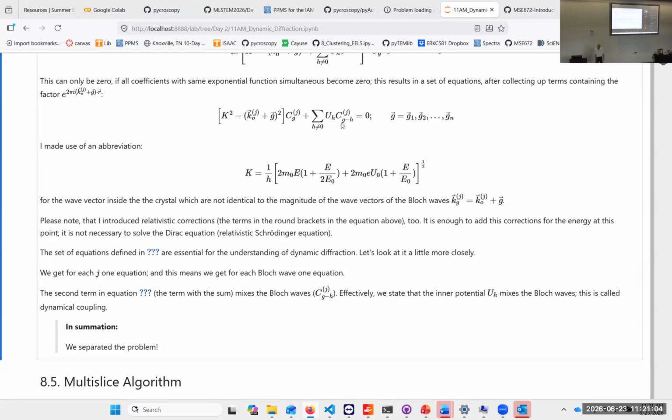So we have the first one going, and in our simple picture this one is connected with a spring. Then at some point the second one starts being activated, so we get diffraction. And funny enough, at some point all the intensity is in the second pendulum, our diffracted beam, and then it gives it back. So with two pendula, I can do that with my hands.